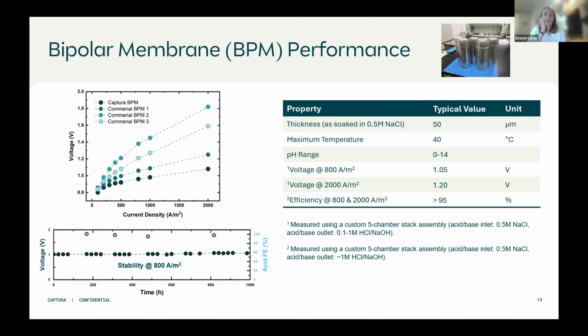Additionally, we use some of these cells to run voltage stability tests. So this example here is one of our membranes run for 1,000 hours, holding at 800 amps per meter squared, and it holds the same voltage of around 1 volt for this entire run.